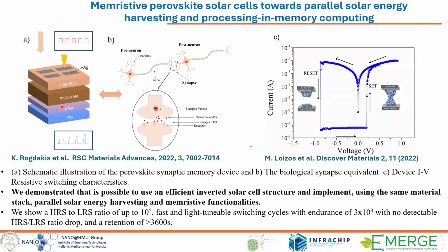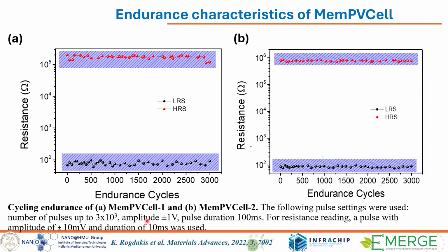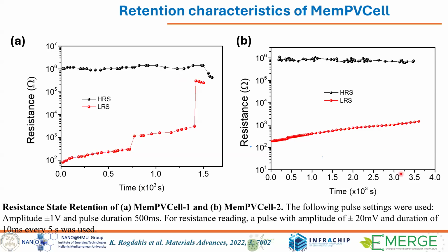Okay. So very briefly then. As I told you, we started with the standard solar cell structure. So this is an inverted solar cell structure with mixed halide perovskites, 4 cations as the active layer. A typical IV switching characteristic is shown here. You can see we have a quite good ratio between high and low resistance, 10 to the 5. Set voltage quite low, 200 millivolts, and a reset of 0.8 volts, more or less. We have demonstrated also typical endurance cycles, more than 3,000, and retention characteristics at least 3,000 seconds for some specific configurations.